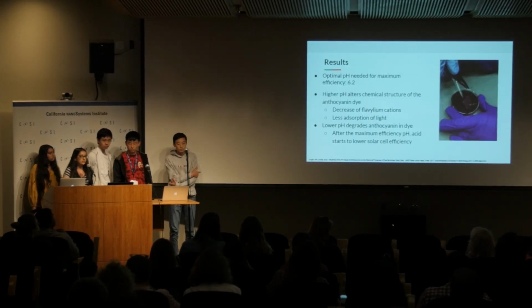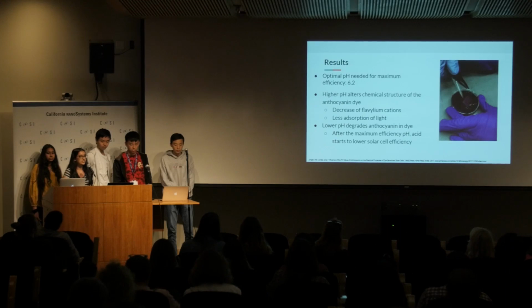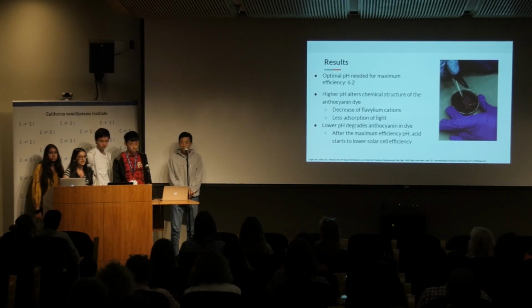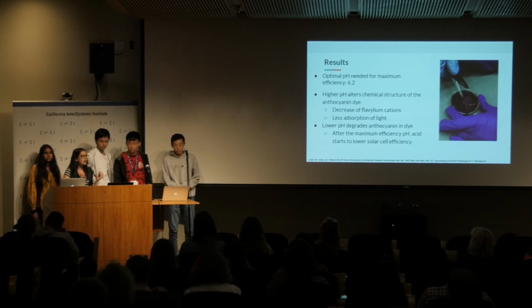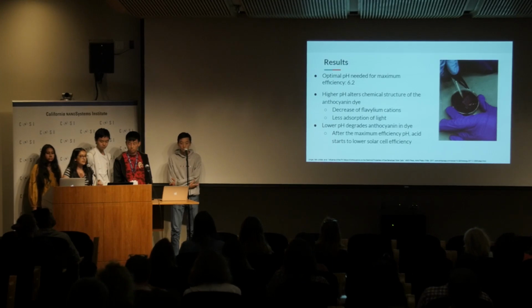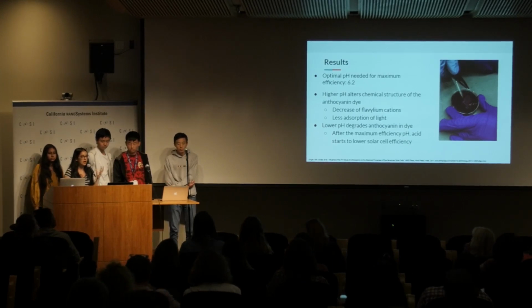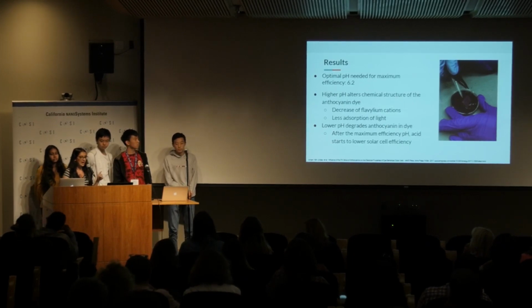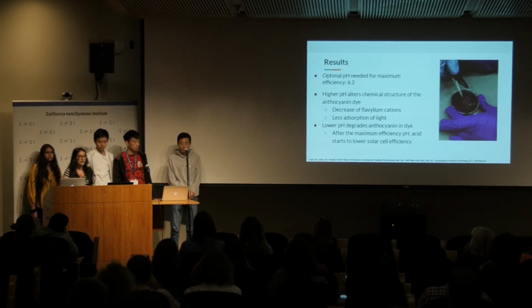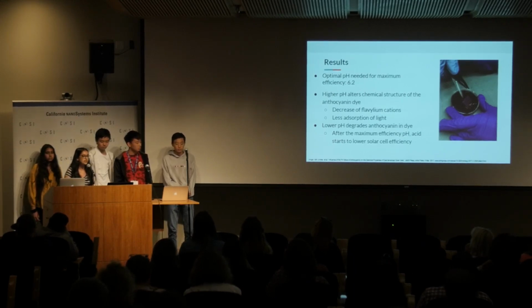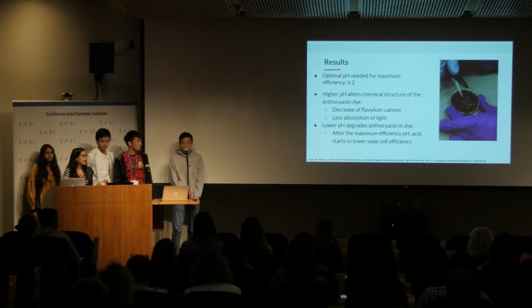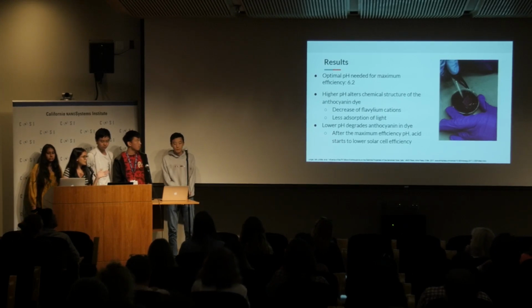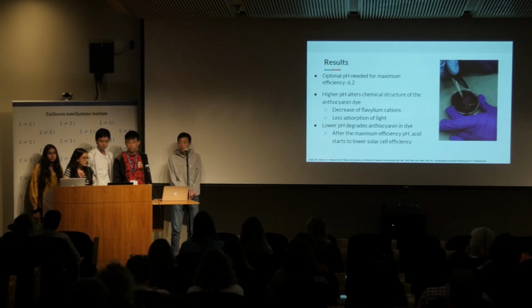So we found that if the pH is too high, it was due to a chemical deformation in the structure of the anthocyanin dye, more specifically in the flavylium cations in the anthocyanin dye. So anthocyanin is the colored part of the beet juice. And because there was a lack of flavylium cations, which is the part of anthocyanin that absorbs light, if there's less of these cations, it will absorb less light. And because there's less absorption of light, there's less current produced, therefore it's less efficient. And with the lower pH, we found that too low and too acidic of a pH starts to degrade the properties of the dye. And so what we found is that after the maximum efficiency pH, acid starts to lower solar cell efficiency.